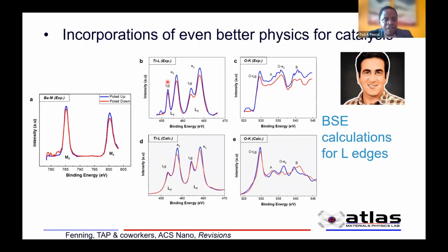Yeah. But if you look at the t2g and eg peaks, for instance, for the L3 and the L2, they are being modulated by different amounts. It's not just a uniform modulation of the features. And we've done the paraelectric phase effectively of this material. Okay, that makes a lot more sense. It's all within expectations in that the paraelectric phase lies in between these two extremes in terms of spectral intensity.